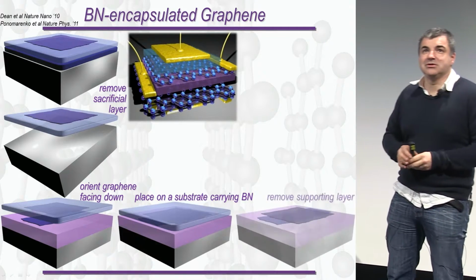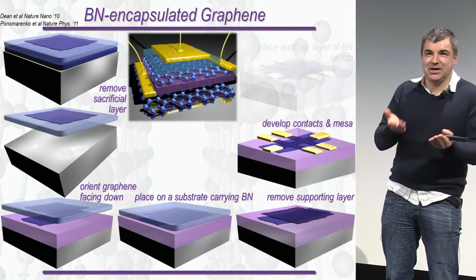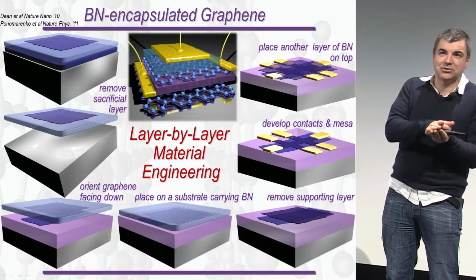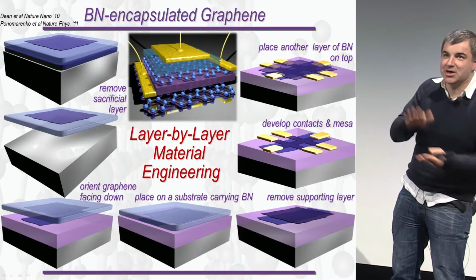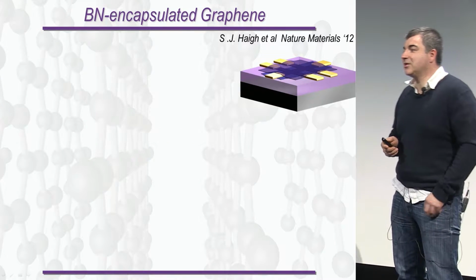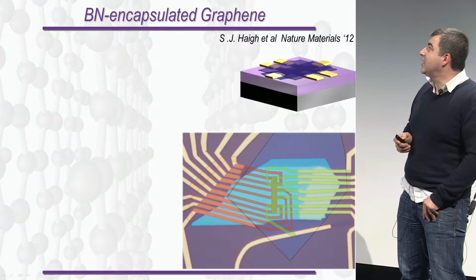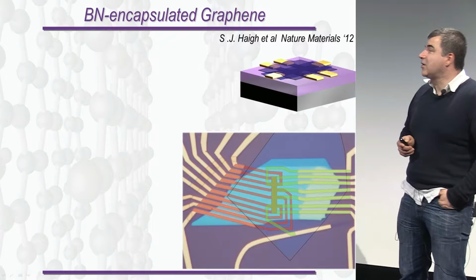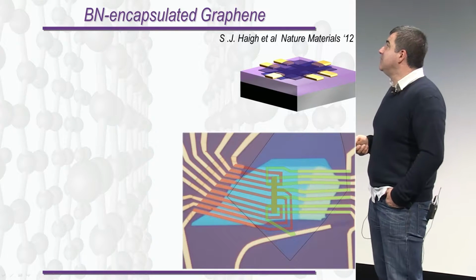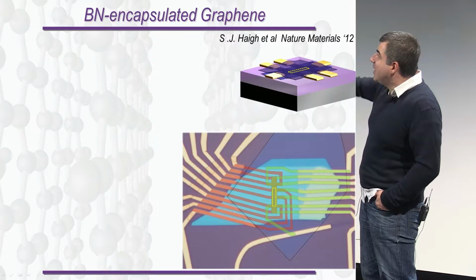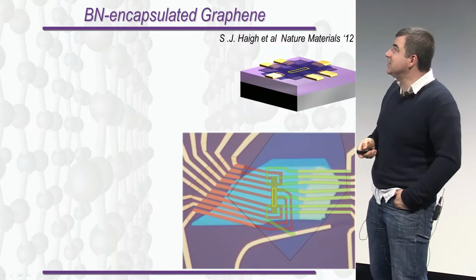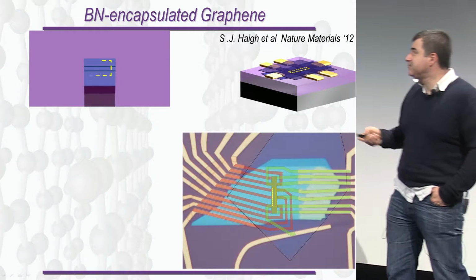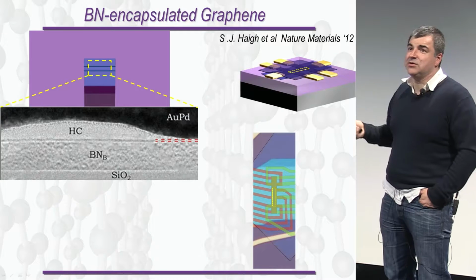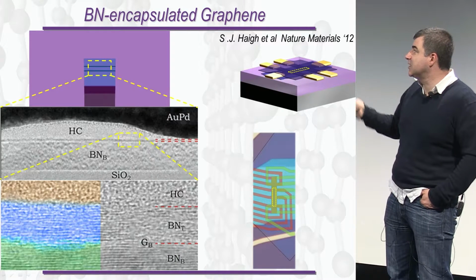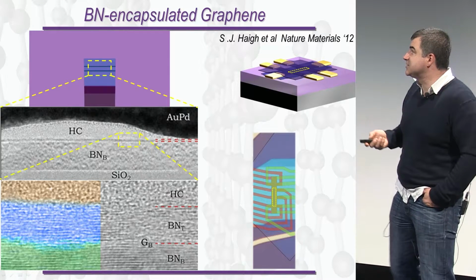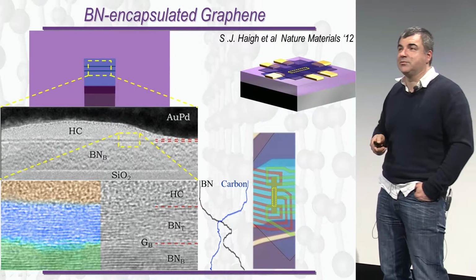But basically, our students do exactly what I said: take one atom thick fabric, put it on top of another, take another one, put it on top of another, and just do it for many layers. But because we can control it very well, I can show you the quality of the resulting heterostructure can be extremely high. So we can take this heterostructure, cut it, pull it out, and look at it in the TEM, and you can see all the individual layers. Those lines are individual layers, and here is boron nitride and graphene layers together, and you can see all the sequence without much contamination.